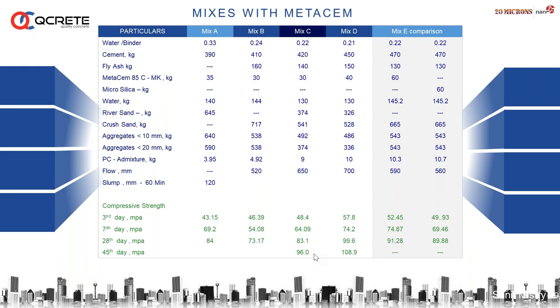And you can see mix D also. It is giving a good flow of almost 700. The mix is 450, 150, and 40 kg of metakaolin we added here. And the strength part is crossing almost 100 MPa. Concrete is possible to design using such a kind of mix with Metakaolin. Even during the experiment, we tried keeping the comparison between the other available mineral admixtures and this Metakaolin.